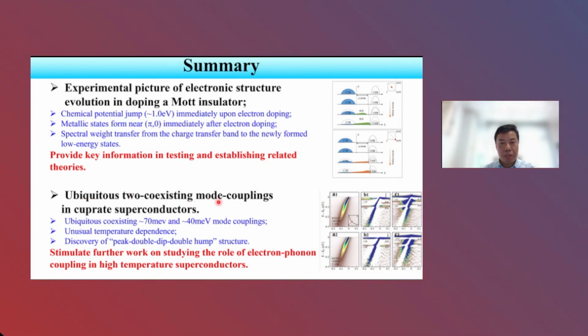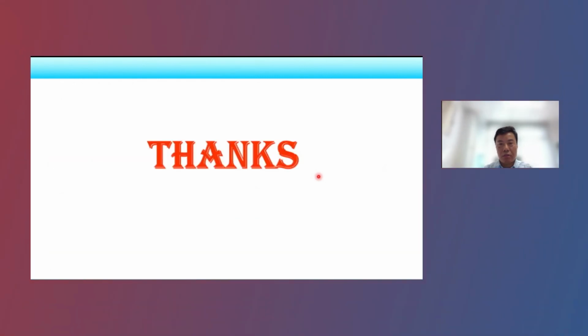The second topic is that we have really observed ubiquitous mode coupling, electron-phonon coupling, in cuprate superconductors. Mainly the 70 millielectronvolt and 40 millielectronvolt mode couplings, coexisting, are present in different materials, different dopings and different temperatures. It's truly ubiquitous everywhere, but it shows very unusual temperature dependence. We have also discovered that the EDC consists of a peak-double-dip-double-hump structure. I hope this work can stimulate further work on studying the role of electron-phonon coupling in high temperature superconductors. Since my time is up, I conclude here. Thank you for your attention.